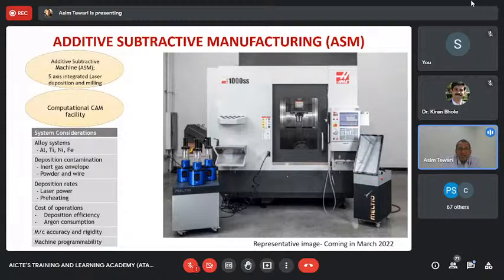And this is a 5-axis additive subtractive machine, which means that you can do an addition as well as subtraction right in the same machine. And this has capabilities of both powder as well as wire feed. And we can pretty much do any alloy. We can do aluminum, titanium, nickel, iron, even copper has been tried on it. This is with a laser source, and this is a directed energy deposition based system.